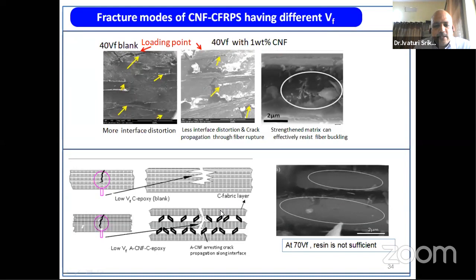But if you compact it very well, there is no gap from one layer to the other layer. There is no thin or thick matrix layer. Then these fabric layers themselves are interlocked. There is no need of CNF. So crack cannot propagate through the interface. Crack has to propagate through the intralayer, interlayer, like this, across the thickness. So in such cases, the role of CNFs is marginal. In fact, they may negatively affect also. That's what we have identified.